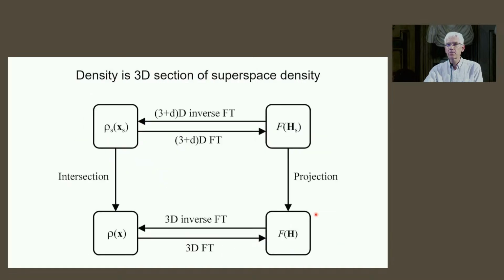And that brings us to the central scheme of the superspace description by Janssen, Janner and de Wolff. At the bottom half we have physical space with an electron density governed by all the atoms at their positions. Then we can do a Fourier transform in physical space, and we get the structure factors. And the square of the structure factor is the intensity of the Bragg reflection.